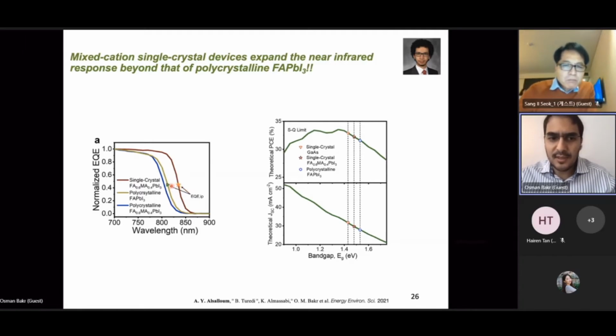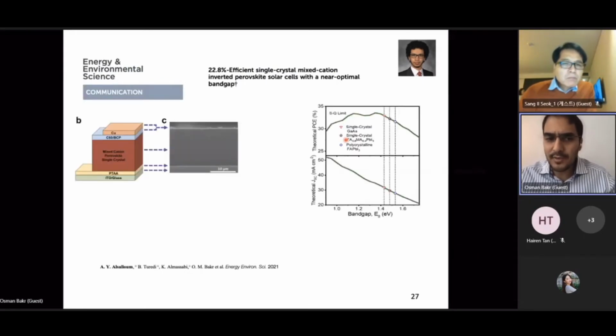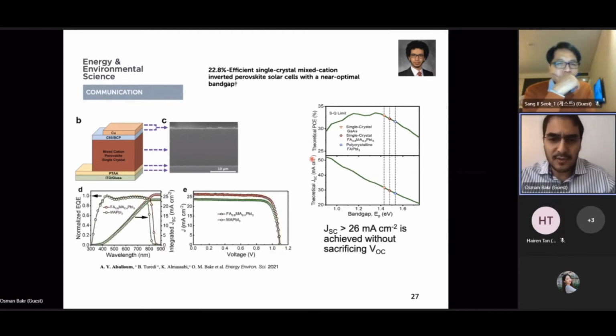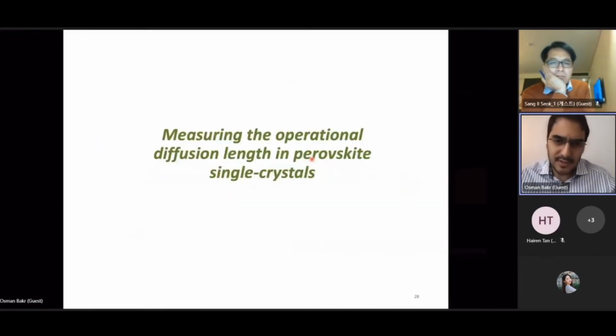So we ended up shifting the EQE spectrum even a few tens of nanometers beyond what people are familiar with from just polycrystalline lead iodide, and we were closer to the sort of band gap that we would like to get from ideal materials like gallium arsenide. And because of that, we were able to improve the efficiency even further, push it to 22.8%, and that was a big step for our field. And the surprising thing is to see that mixtures of formamidinium and methylammonium would give us a significant shift beyond what we normally had expected from just pure formamidinium. And we have very large short circuit current densities.